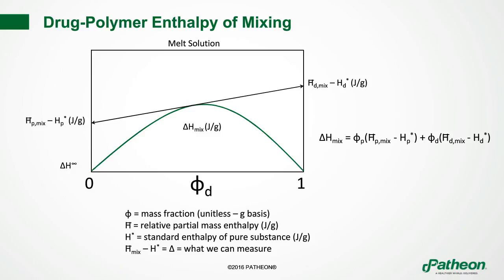As you see, as you go from 0 or 0% drug all the way to 100% drug over to the right where it says 1, you can see that your heat of mixing is going to take on this parabolic shape. So somewhere in the middle is where you're going to have your maximal heat of mixing. Obviously, if there's no drug, there is no heat of mixing. And likewise, if there's no polymer, where drug is 100%, there's also no heat of mixing. Therefore, you expect those values to be at 0 on the y-axis.